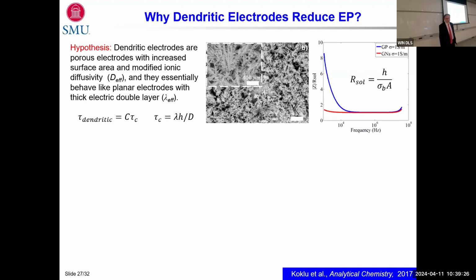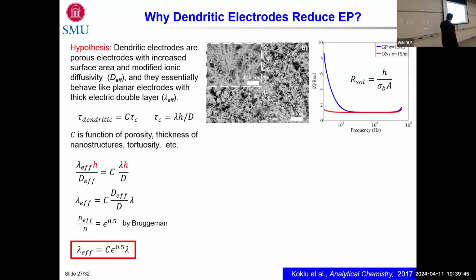So can we actually model this difference? Why don't we shift our time scale for dendritic electrodes with a coefficient C? And of course, tau is lambda h over D. So that C will be a function of porosity, thickness of nanostructures, and tortuosity. But when you work that out, you can actually put on the left-hand side an effective double layer thickness, because that's the idea, and then the diffusivity within that medium, which is going to be effective as well. So you have the heights here, which are common, and that goes away. So that's the electrode separation.